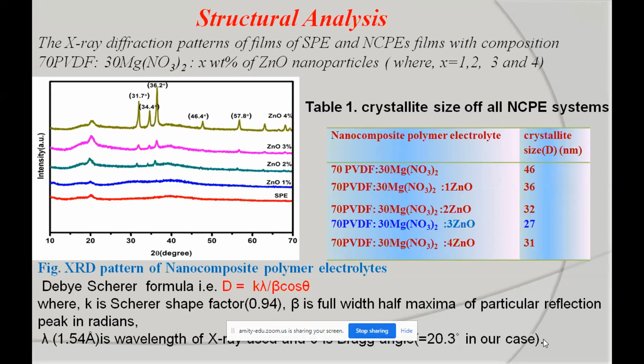And using this curve, we can also calculate the crystallite size by using Debye-Scherrer's formula, that is D is equal to K lambda by beta cos theta, where K is the Scherrer shape factor, beta is the full width at half maxima of a particular reflection peak, and lambda is the wavelength of X-ray used. And this is a table representing the crystallite sizes of all nanocomposite polymer electrolytes, and we got the minimum crystallite size for our optimum system, that is 70% of PVDF, 30% of magnesium nitrate, and 3% of ZnO nanoparticles.